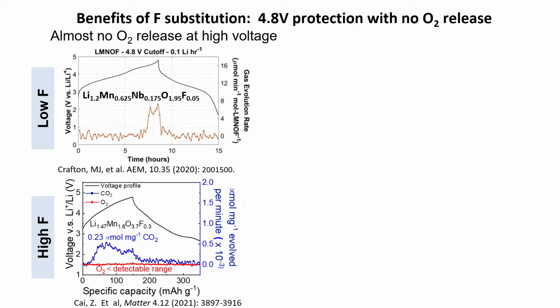This gets a little more technical, but many cathode materials have gas release when you charge them to high voltage. And what happens with fluorine is that this is actually DEMS data, where you charge a cell and measure the gas coming off, and there is only a very small amount of oxygen coming off, even at high voltage, much less than a classic material.